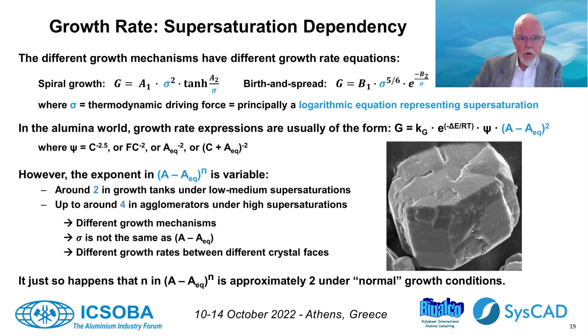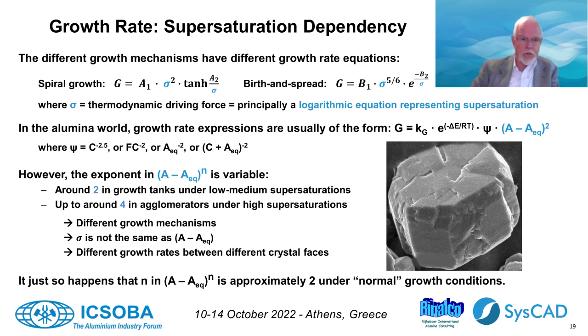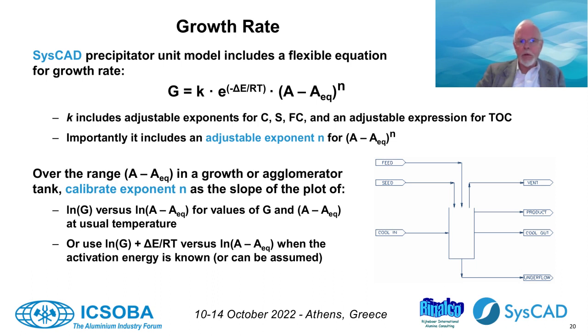The variability is not only because of different growth mechanisms and because of A minus A-equilibrium not being equivalent to sigma, but to some extent also because of different growth rates between the different crystal faces. This is not new, but it is also not common knowledge. The SysCAD precipitator unit model accommodates a flexible growth rate equation in which, for instance, the exponent for supersaturation is adjustable. We will find and specify a different exponent for growth precipitators than for agglomerators. You will find the exponents through log-log plotting of growth rate against A minus A-equilibrium over the applicable ranges for the particular precipitator or group of precipitators.